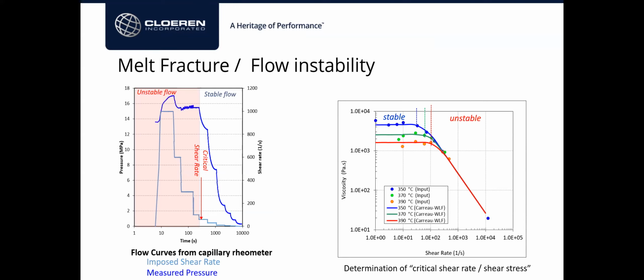Do you consider wall slip on die flow simulations? Typically not, and the reason is that characterizing the slip, as I mentioned, the Mooney method, similarly to Bagley or the historical Bagley, you have to use many different dies, and it's more like a research project. We have ways to deal with that without saying too much, that we know how to correct for it versus actually modeling the slip in the flow simulations.